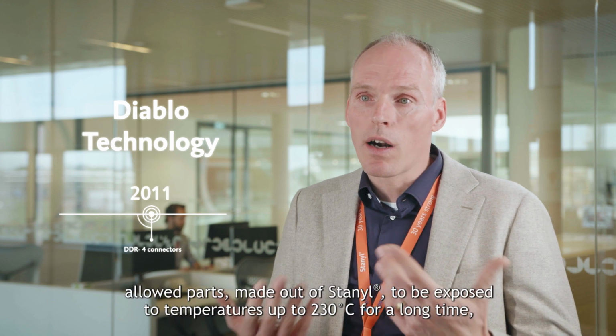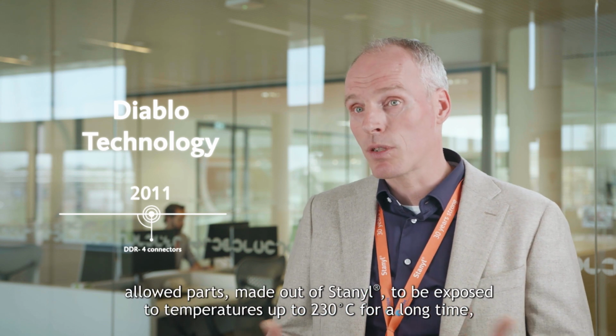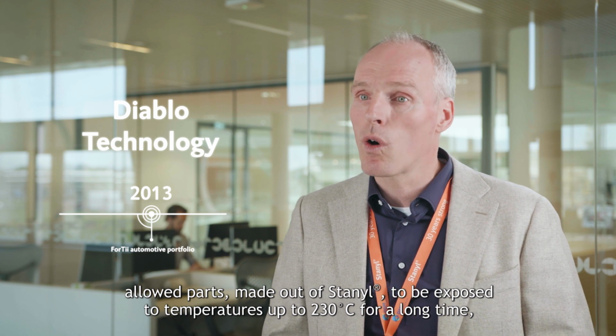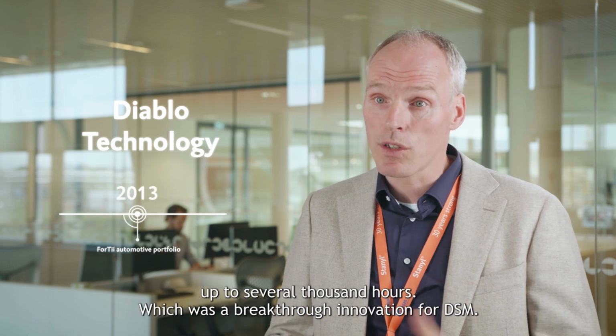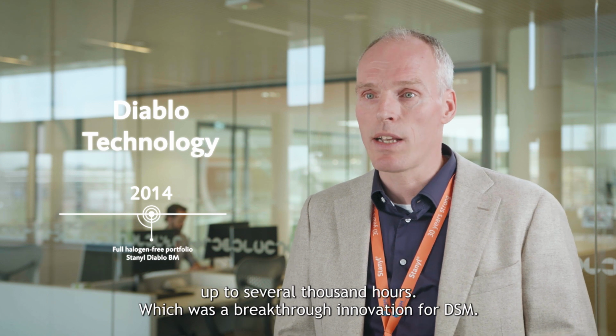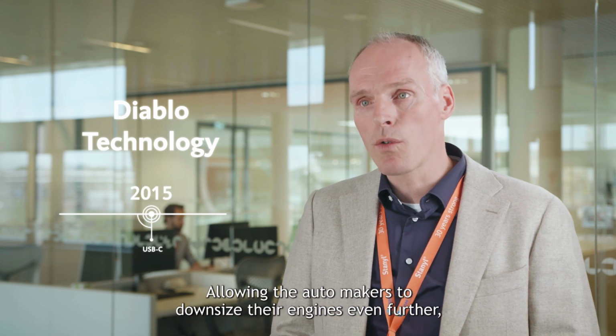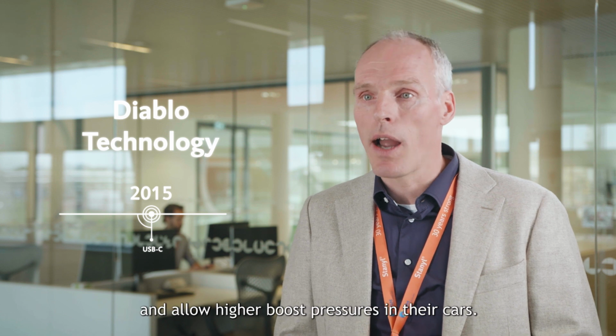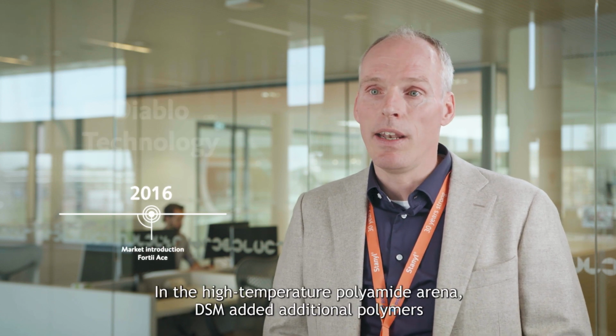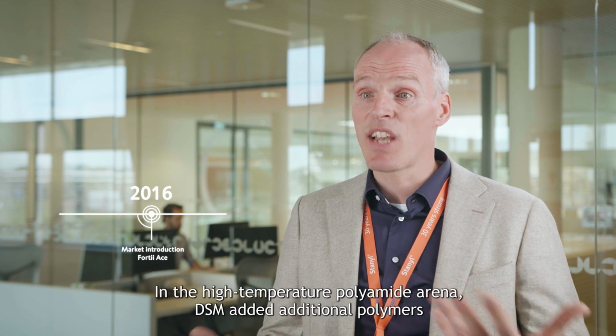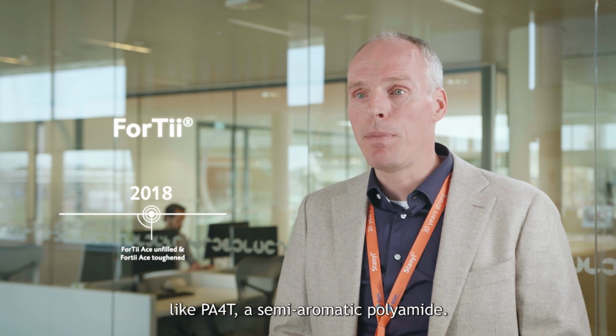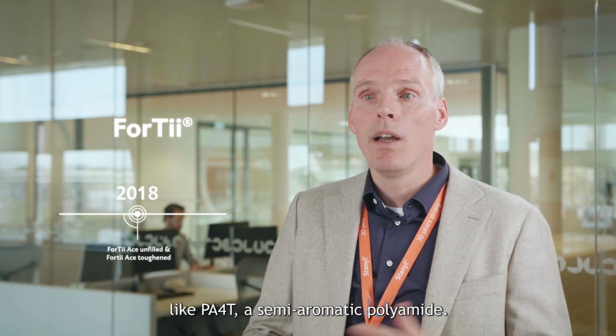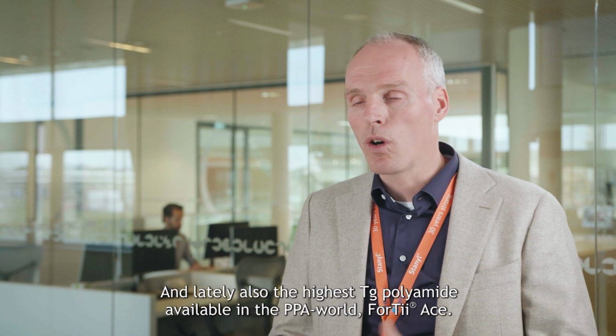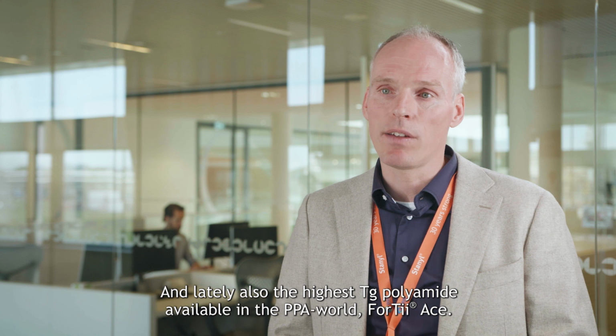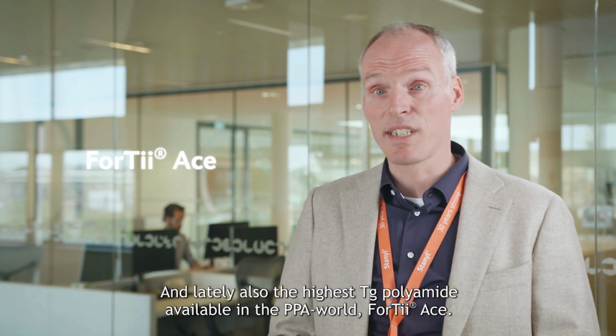The invention of our Diablo technology allowed parts made out of Stanyl to be exposed to temperatures up to 230 degrees C for a long time, up to several thousand hours, which was a breakthrough innovation for DSM, allowing the automakers to downsize their engines even further and allow higher boost pressures in their cars. In the high-temperature polyamide arena, DSM added additional polymers like PA4T, a semi-aromatic polyamide, and lately also the highest Tg polyamide available in the PPA world, ForTii Ace.